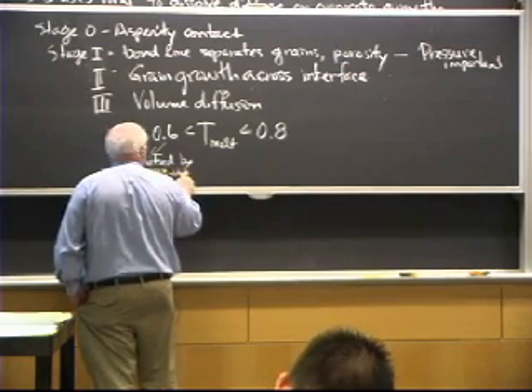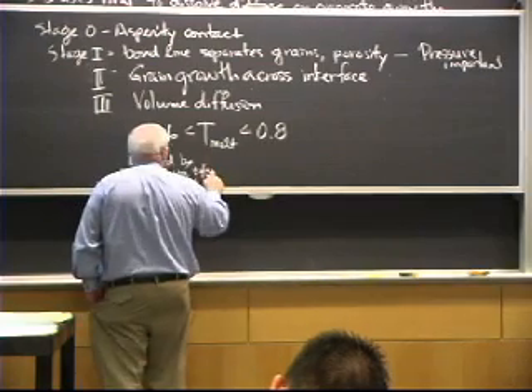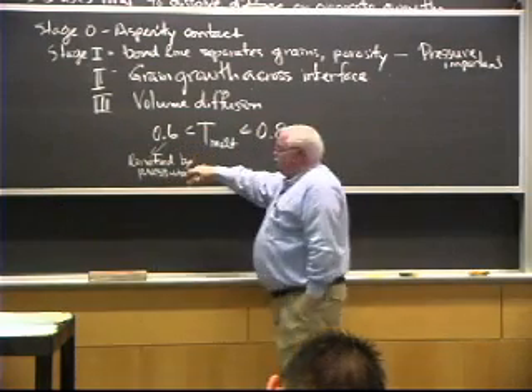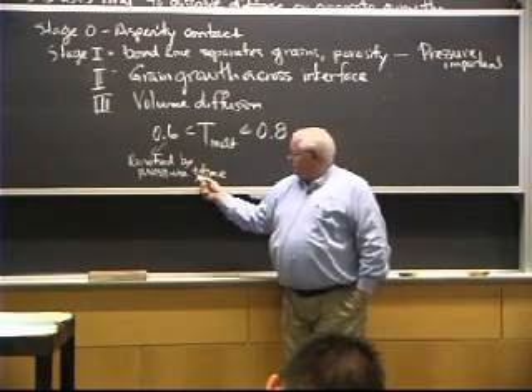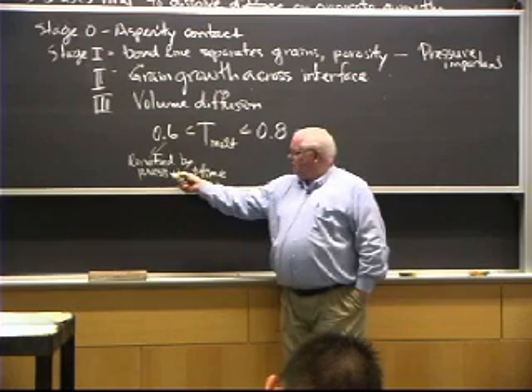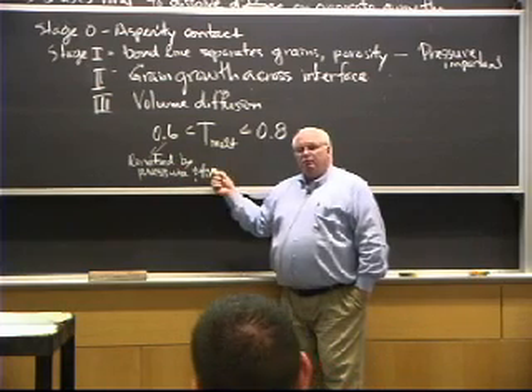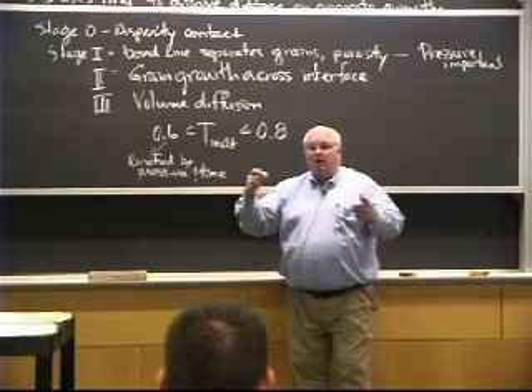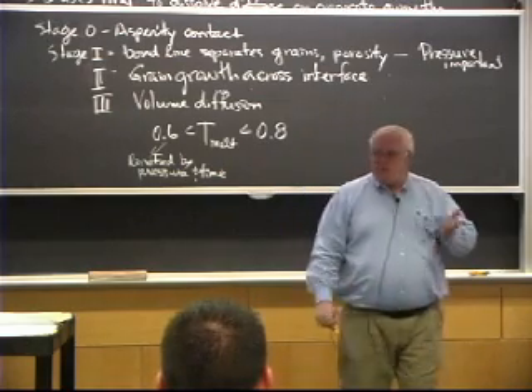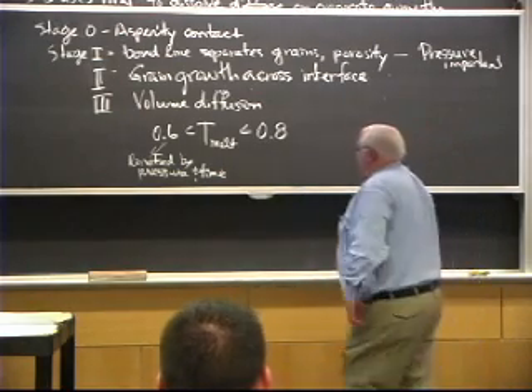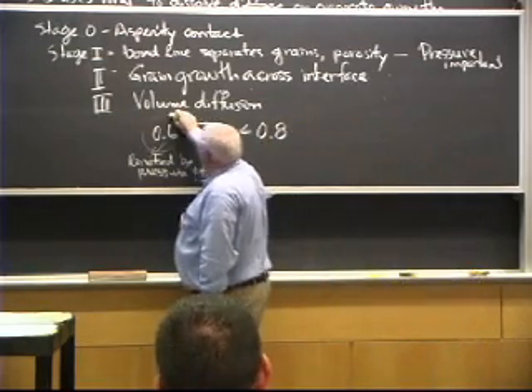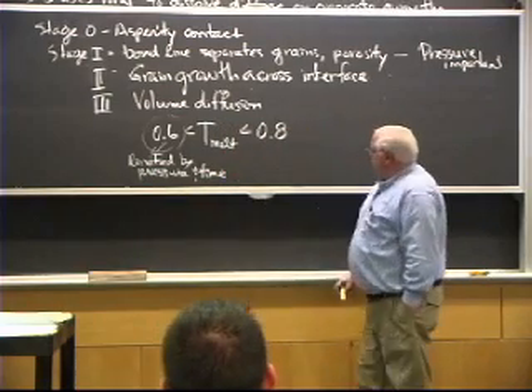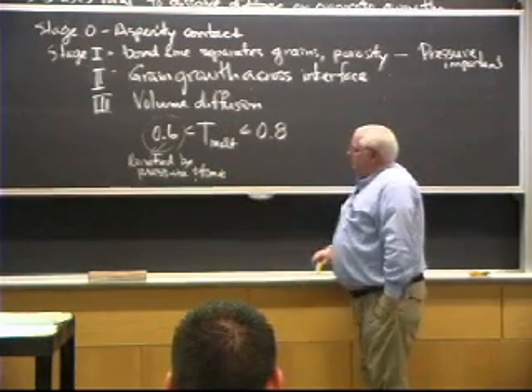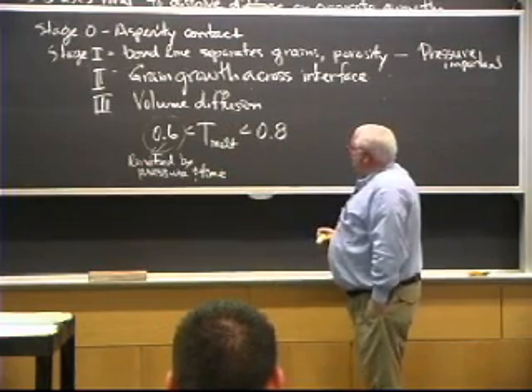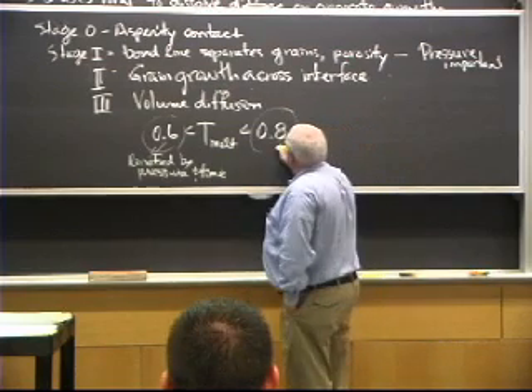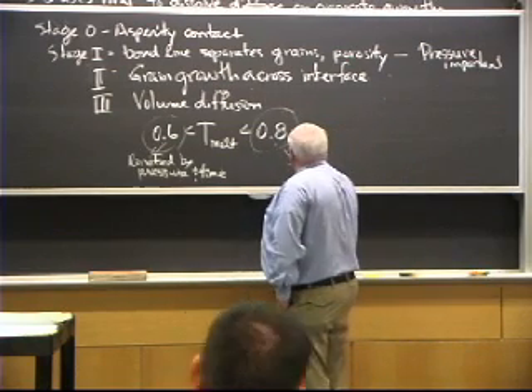and time. The rate of diffusion goes exponentially with temperature, and so not only does my pressure go shooting up, but my times go shooting up, and it may be hundreds of hours rather than tens of hours. And so I have to get enough heat in, and typically that's somewhere around 6/10 of the absolute melting point to not be limited in terms of the cost of processing in terms of pressure and time. Here, above this, I've got a problem of grain growth.